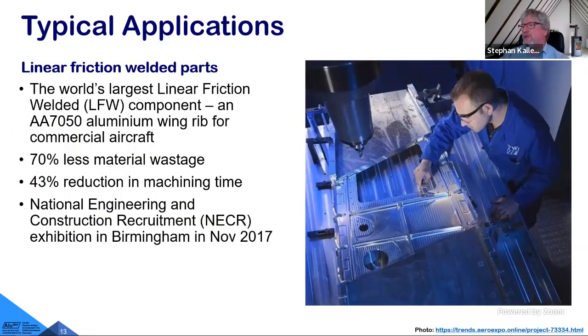The largest linear friction welded part was a component that was near net shape component. And you see the figures here, a very little material wastage. The machining time has been reduced. And we were able, although this seems to be similar to military components in military aircraft, we were able to exhibit that in Birmingham. But indeed, the military aircraft industry is the one that uses the process the most for near net shape manufacturing. And they don't talk about what they really use it for, but for similar components like shown here.